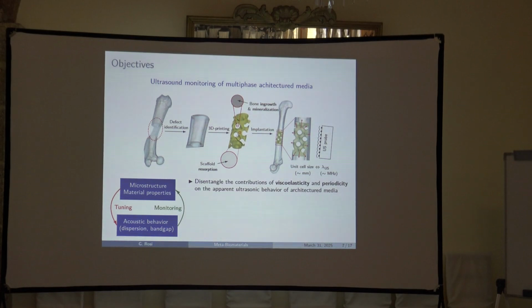Okay? So during the thesis, in order to arrive at the proof of concept that we present to you in this work, we did some preliminary studies to study the effect of viscoelasticity, for instance, because these materials are highly viscoelastic. We had to identify which kind of ultrasonic signature we want to use, and we decided after a while to use only reflection, because we cannot measure transmission when you imagine that we are putting this probe in a bone, so you have outside the skin, so you will have a thin layer of soft tissue, and it's much easier to measure the reflection than the transmission on the other side.